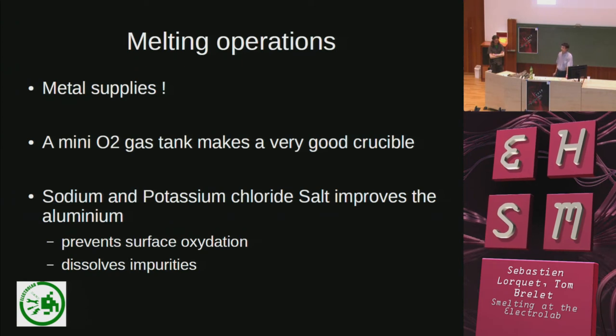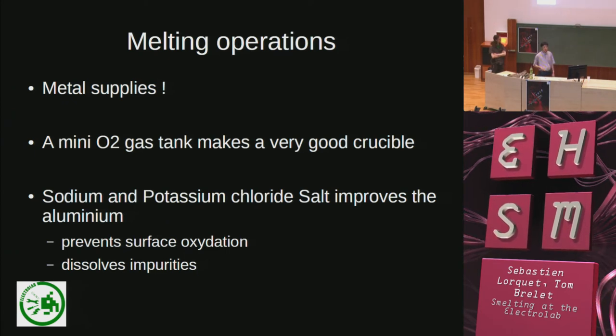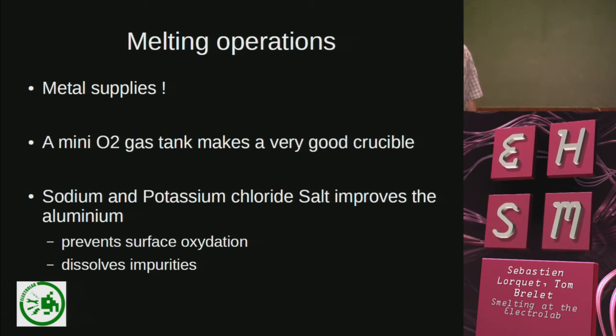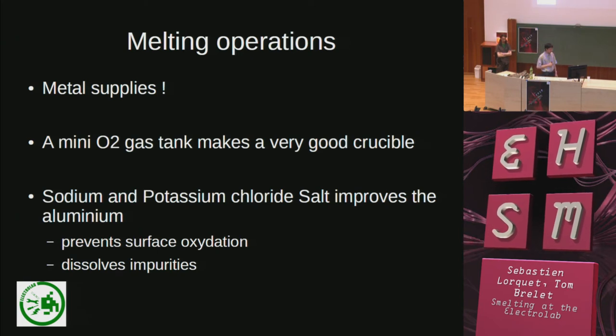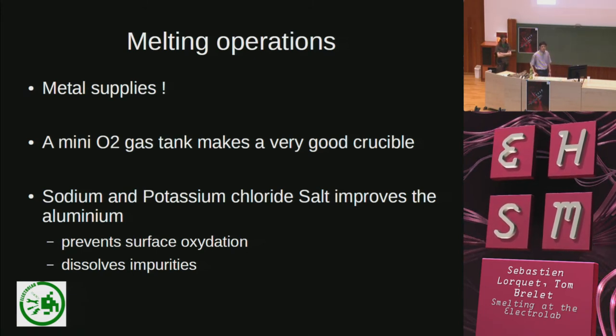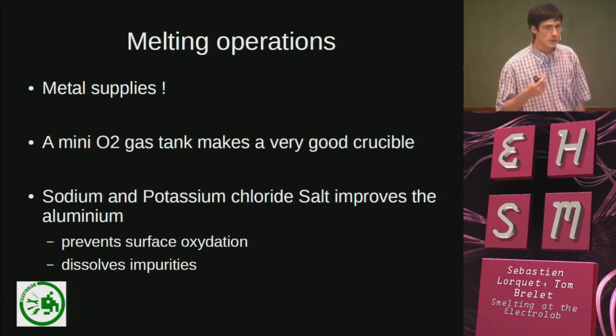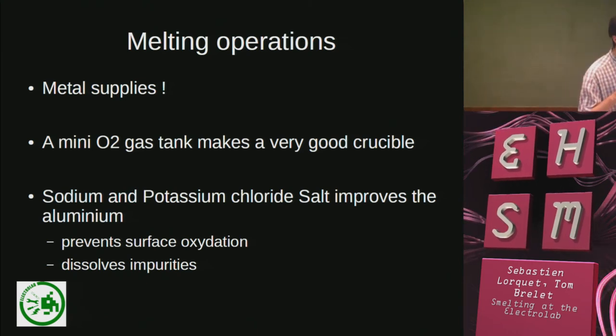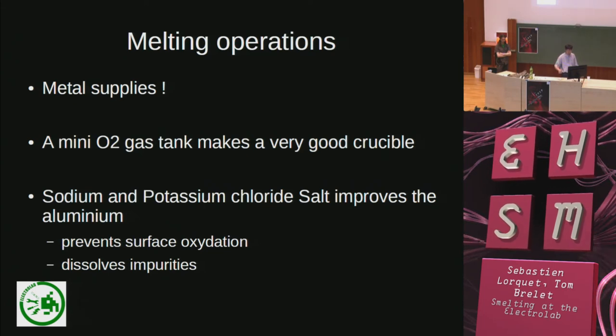The crucible was very conveniently hacked from an oxygen tank, you know, from a soldering torch. This is very easy to find, very cheap, and very strong. It's made of steel, very thick steel, so it doesn't melt easily. There is a problem, I'll just tell you now because it's about this point. The steel crucible will have problems with aluminium because the steel from the crucible will melt with the molten aluminium. And this is not good for the purity of the metal. One thing we learned from the web and rediscovered by ourselves is that we need to add some salt into the aluminium to improve the solubility of impurities and to get a very clean metal. Without this, there is a lot of dirt on the surface, and this causes a lot of problems when we try to pour this molten metal in the mold.